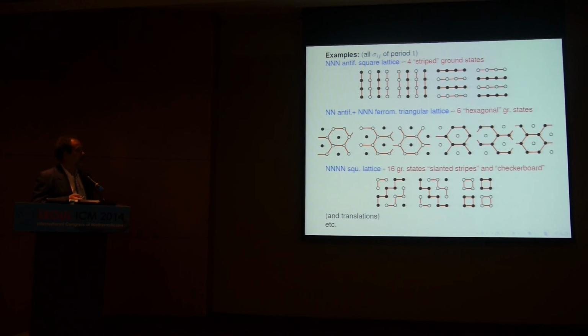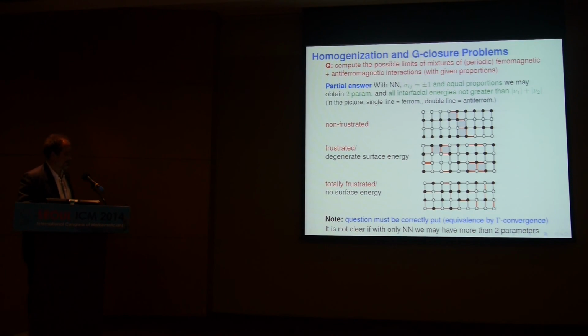So for example, for the next to nearest neighbor interactions, you can have 4 types of striped patterns and interfaces between them. If you add a ferromagnetic interaction to the triangular antiferromagnetic lattice, then you stabilize and you obtain 6 parameters. Then you have something described by 6 ground states. Here you have another case in which you have 16 ground states, and of course, as you increase the number of interactions, you can have more ground states. And now everything becomes more difficult in this framework.